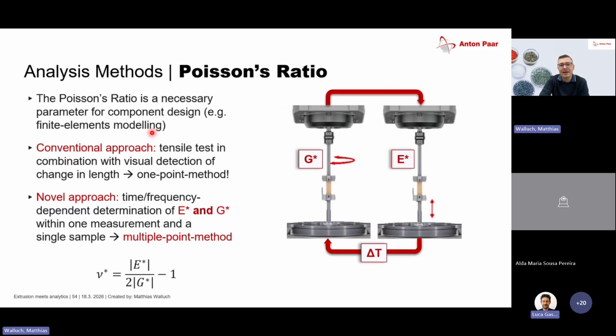And one last thing that I want to mention is a nice feature of our device. So as I mentioned, we can do rotational measurements with the upper drive, and we can do extensional measurement with the lower drives on one sample. So we don't need to change the sample. So we clamp it, we do a torsional test at one temperature, we do an extensional test afterwards, we increase the temperature, we do this again and again.